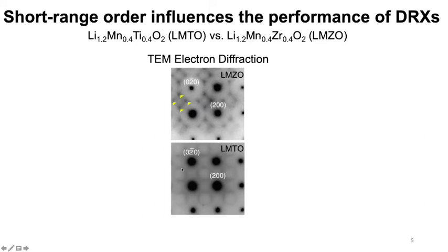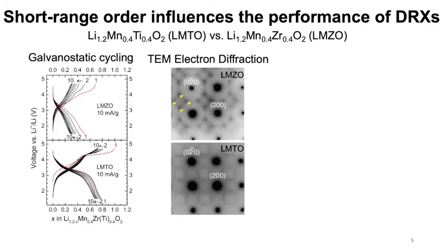And these diffuse patterns here demonstrate the short-range order, and we can see the two materials show quite different diffuse patterns, which means they have very different short-range order types. As a consequence, we can see the LMTO material obviously has a higher capacity, which means more lithium is electrochemically active in LMTO because of this type of short-range order, compared to LMZO, where less lithium is electrochemically active, and that is controlled by this type of short-range order.